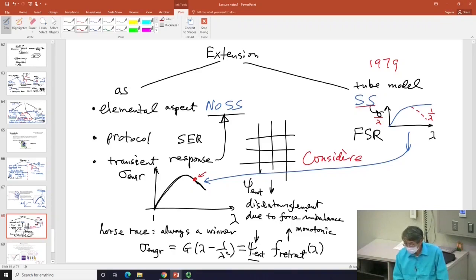The causality reversal that I'm going to indicate one more time, I probably only briefly said it throughout the course, is that this dropping of your force, we know why: disentanglement. It is this disentanglement that produced the dropping. Therefore, the dropping is just the effect, just the consequence of disentanglement.